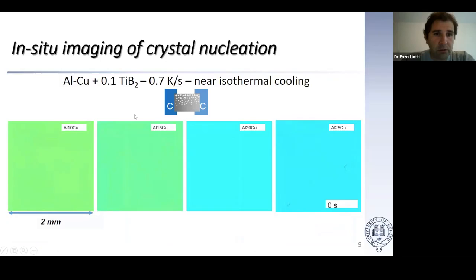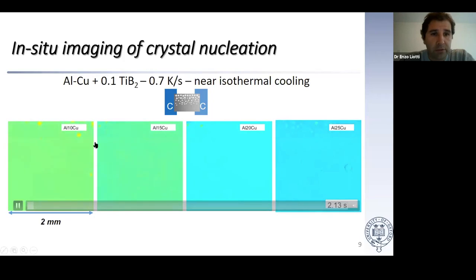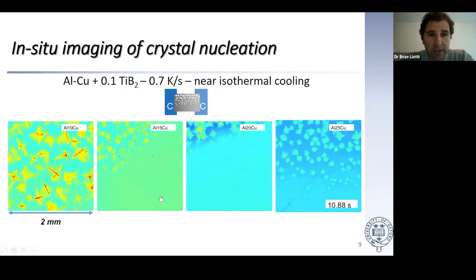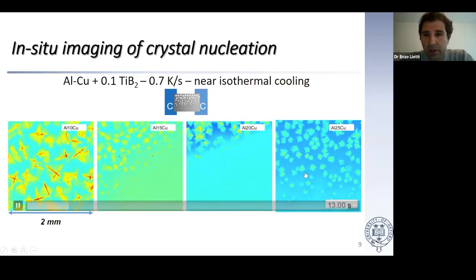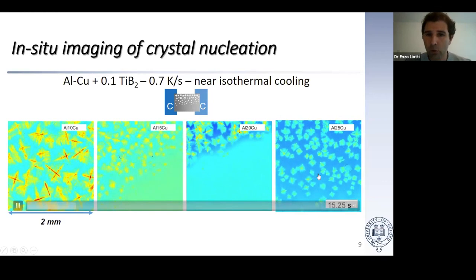In a similar comparison, these show the effect of the solute content, so different alloys. You increase the content of the solute element, in this case from 10% copper to 25% copper, and these 4 samples were cooled at the same cooling rate, which was 0.7 Kelvin a second. Again, there is a lot of variability, as you can see. The color differs, but this was almost raw data, so that's why. But you can see the morphology: these are quite large and form quite quickly, despite the cooling rate being the same in all of them. These tend to be smaller, more equiaxed.